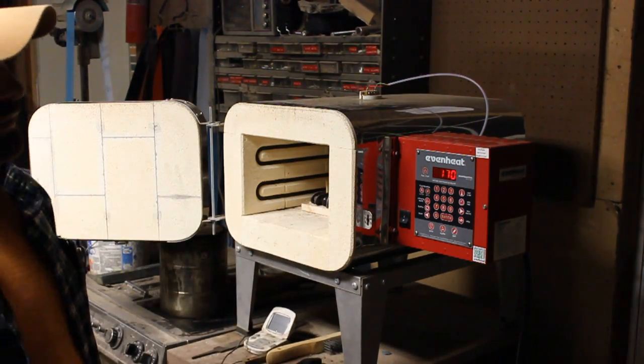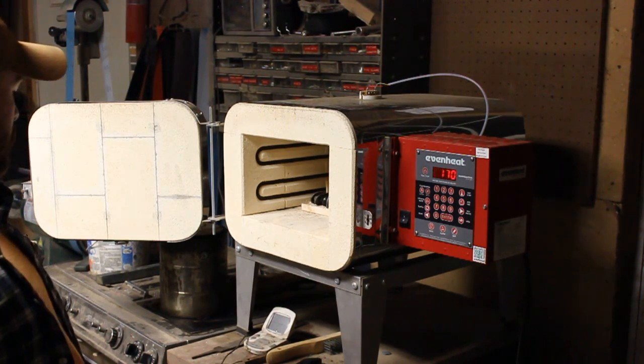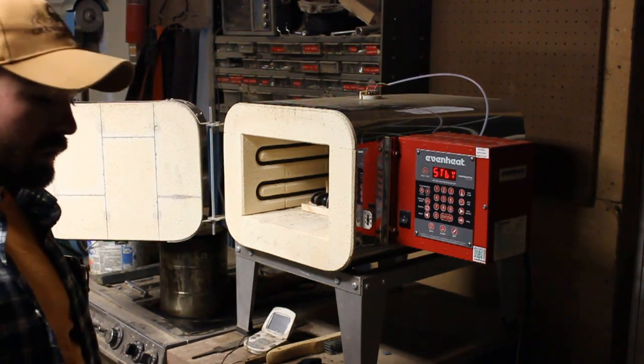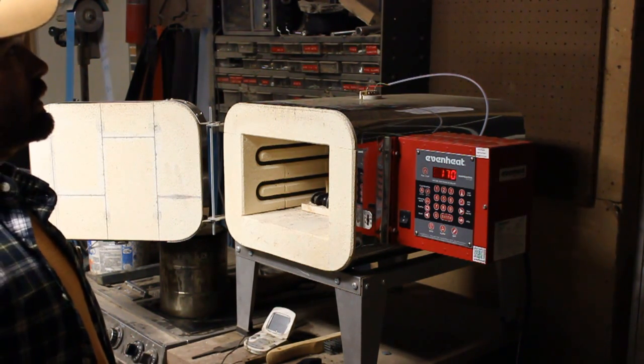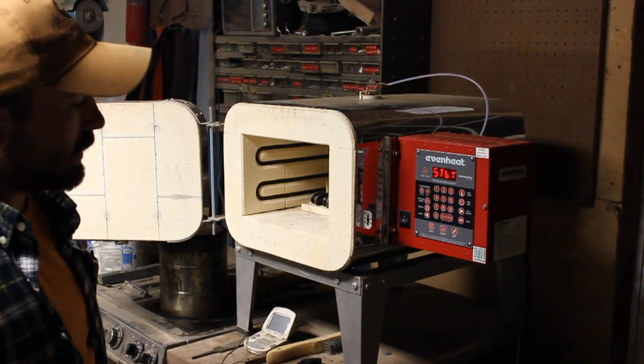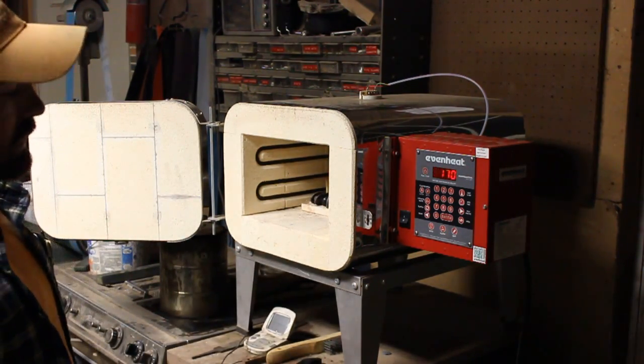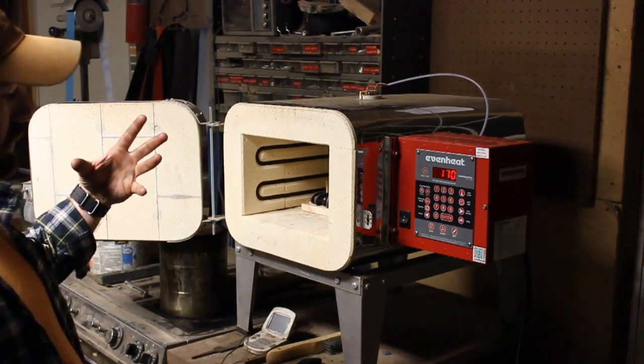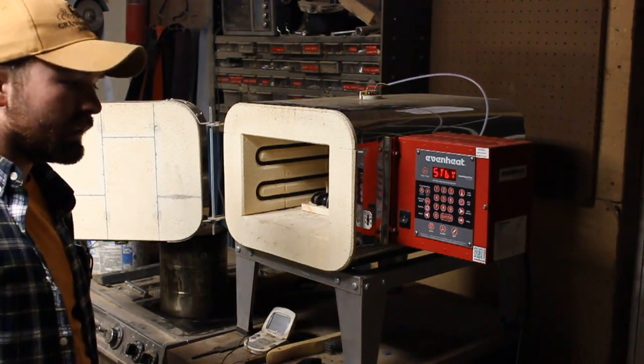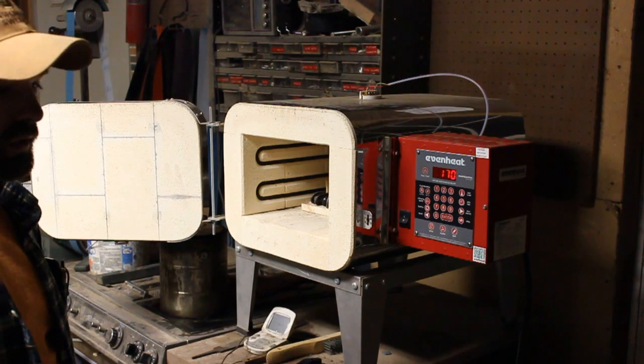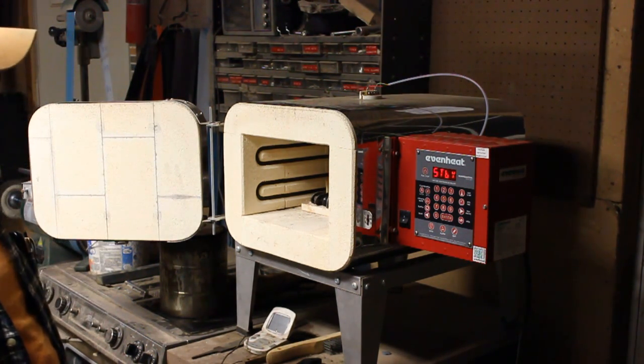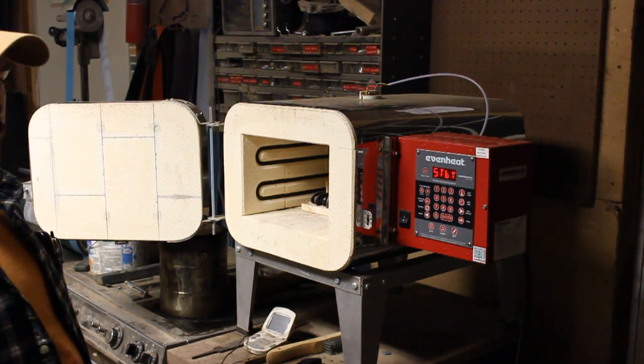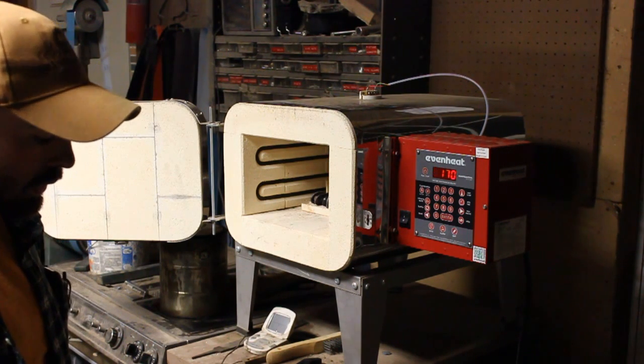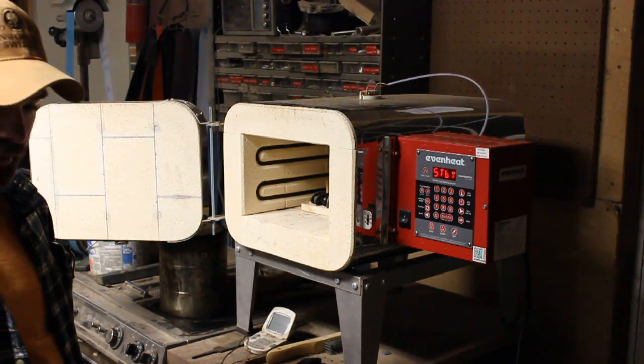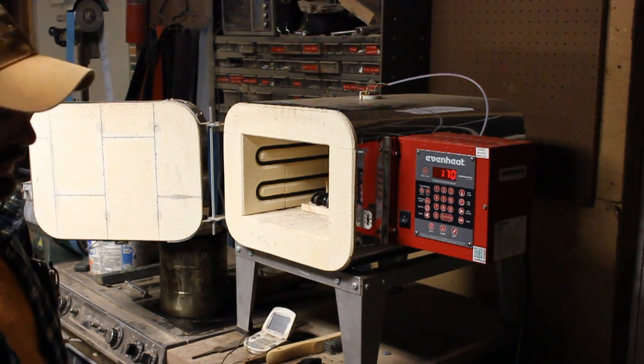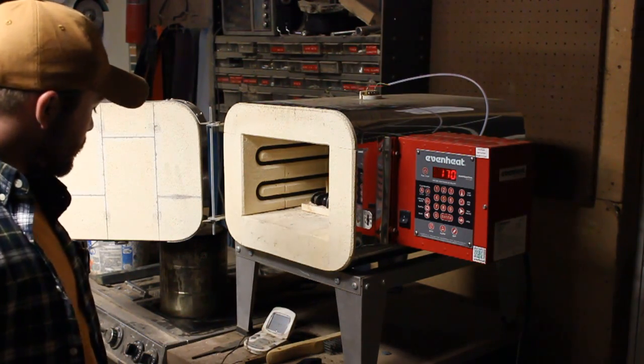The kiln is cooled off. It's only about 170 degrees now. And what I'll do is I don't shut it and just turn it on and walk out. When I'm getting ready to temper, because of some variables, I'll close it up and I'll watch it rise without actually turning it on yet. And by turning it on, I mean applying heat. Because sometimes there's enough heat left in there and just other things, you know, ambient temperature and whatnot. If it's a hot day and I close this thing up and it might be 200 degrees, I'll watch it shoot right up in temperature without even applying heat from the thermocouples or the coils. So I do watch that because you don't want to overshoot your set temp by far at all, because that'll throw off your temper and you'll end up softening your knives to the point that you don't want to.